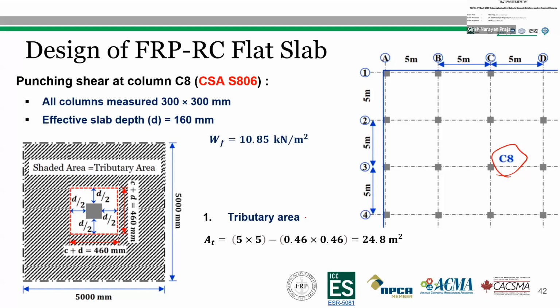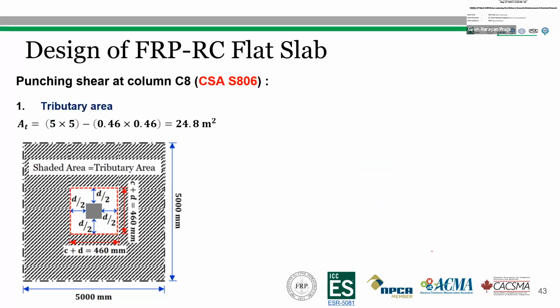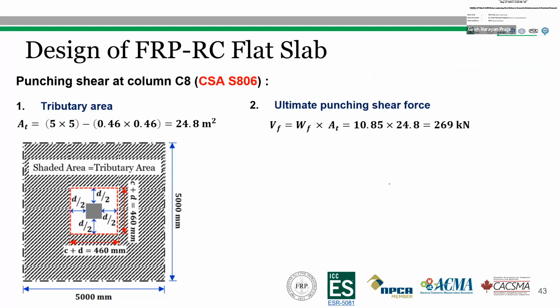Now we need to find the tributary area, and the shaded part is the tributary area, which is the area of the surrounding slab minus the critical shear area, and is equal to 24.8 square meter. The ultimate punching shear force is the factored load multiplied by the tributary area, which is equal to 269 kilonewton. And before calculating the punching shear stress, we need to calculate the punching shear perimeter, which is equal to 4 times the side length of the critical zone, which is 460 by 460 millimeter, and 4 times 460 millimeter is 1840 millimeter.